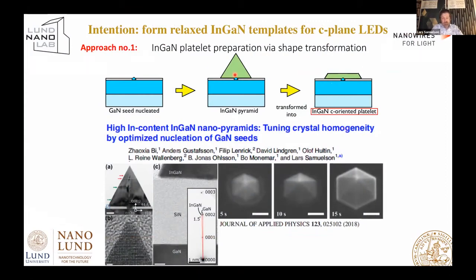We could, with controlled nucleation, you see here some images of Zhaoxia Bi's technology developed initially for the nanowire growth to form perfect seeds that enable you to grow perfect pyramids, hexagonal symmetry pyramids, and then transforming these in an annealing experiment where in principle you make the tip unstable and you're left with just a thin platelet that you can use for the devices. That was the first approach.